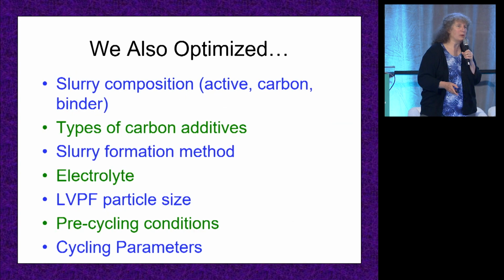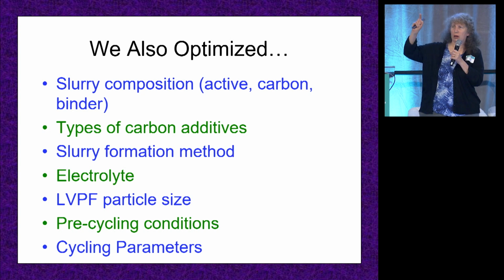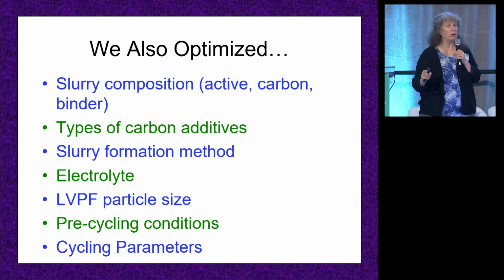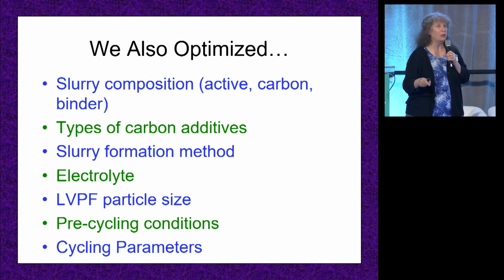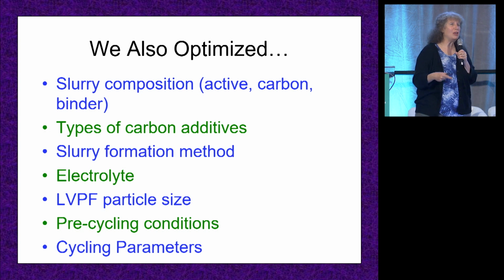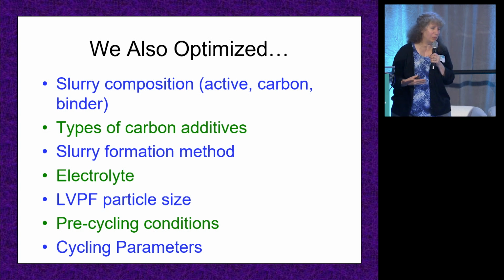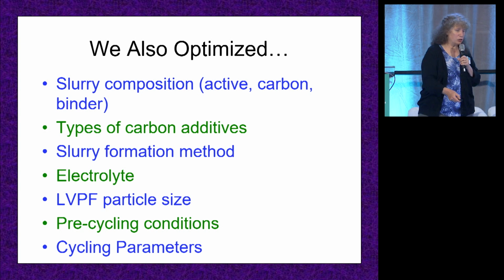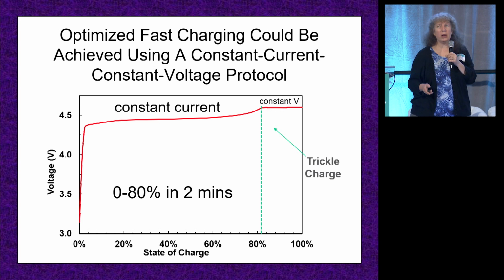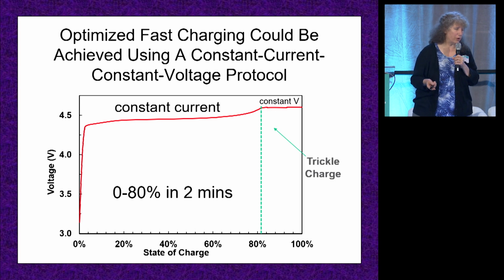We then optimized literally everything about the batteries. I could show you graphs where we look at how fast it charges for every single one of these, but you would probably die of boredom. So I'm just going to make the list of the amazing set of work that Jackie and McKenna did, looking at slurry composition, the type of conductive carbon that they added, the way they formulated the slurry, literally the way they mixed the slurry, the electrolyte, the particle size, the cycling conditions. And the result was a really optimized set of batteries.